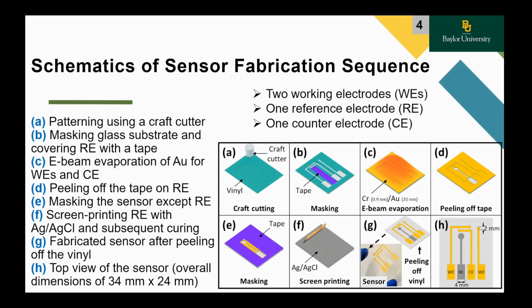Next, the tape on the reference electrode was peeled off and the other three electrodes were masked with tape. The reference electrode was screen printed with silver chloride paste and cured. Finally, the vinyl sheet and tape were removed, leaving behind the compact sensor.